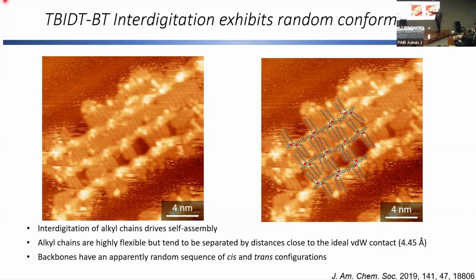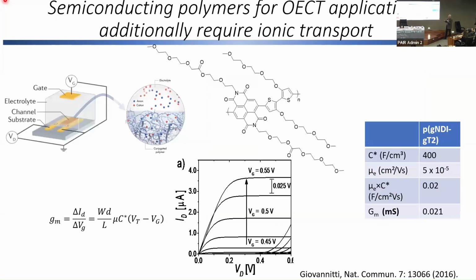So this is our TBIDT STM. This is the backbone here. And this is when we have this arrangement of all cis. You can see that there's a little hole here, slightly larger here. But when you have these large holes, they draw in ambient dopants, ambient contaminants, and these act to reduce the carrier mobility. They introduce disorder into the polymer. So that's not what we want to see.